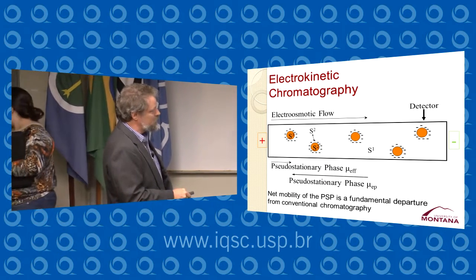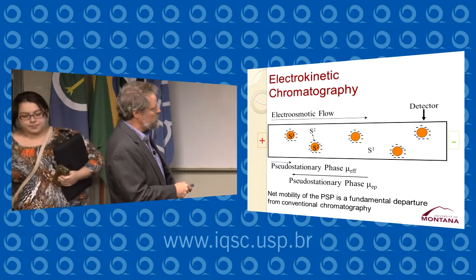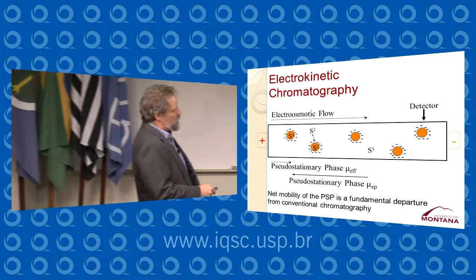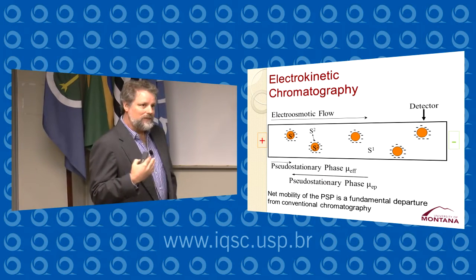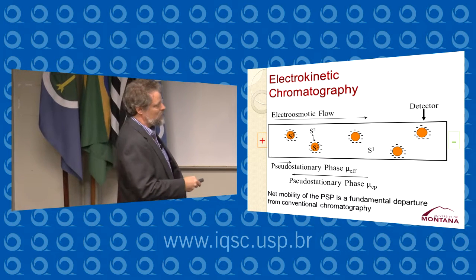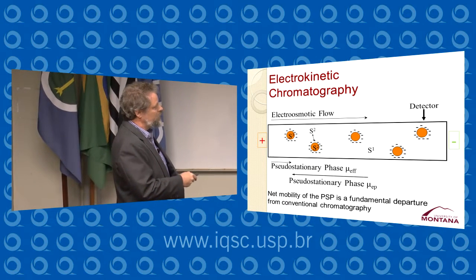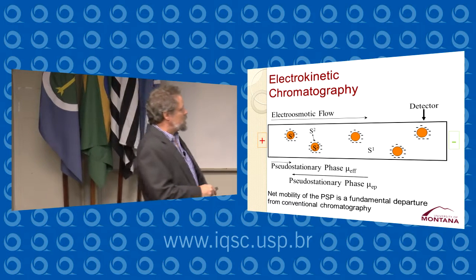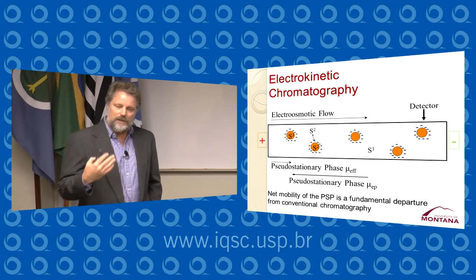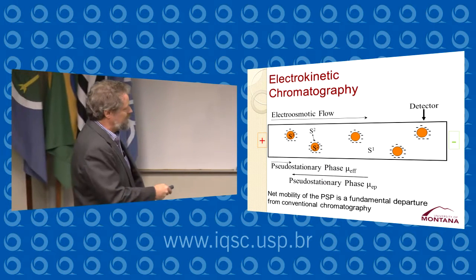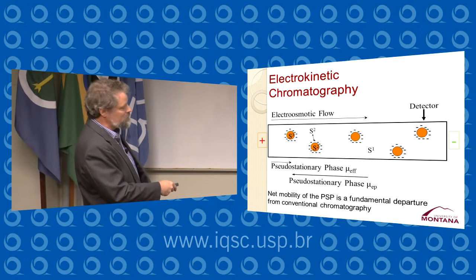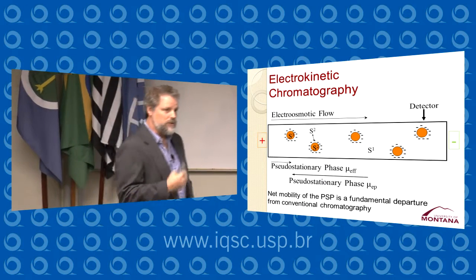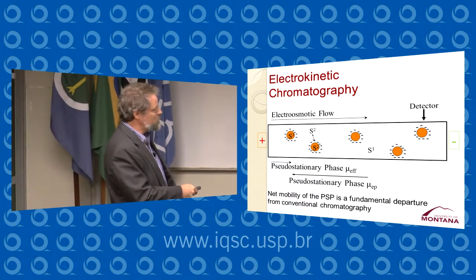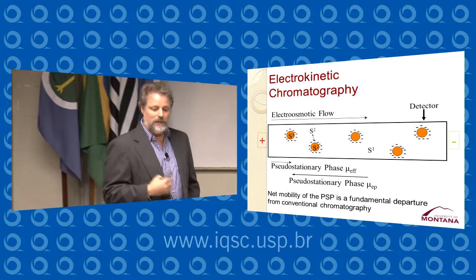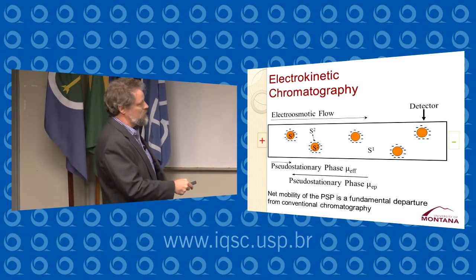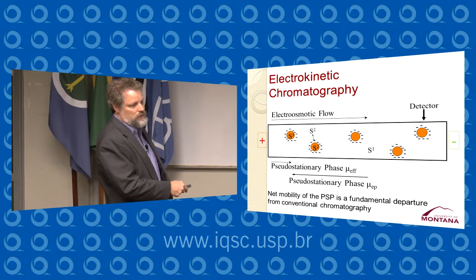Now, if we have compounds that we're trying to separate, like solute 1, solute 2, and solute 3, solute 1 is here to represent a compound that does not interact with the pseudo-stationary phase, does not interact with these SDS micelles. It would migrate at the velocity of the electroosmotic flow. Solute 3 is a very hydrophobic compound that is always associated with the SDS micelles. It would migrate at the velocity of the pseudo-stationary phase. And then other compounds which are partitioning back and forth between the pseudo-stationary phase and the background electrolyte, those compounds will migrate at intermediate velocities between that of the electroosmotic flow and of the pseudo-stationary phase.